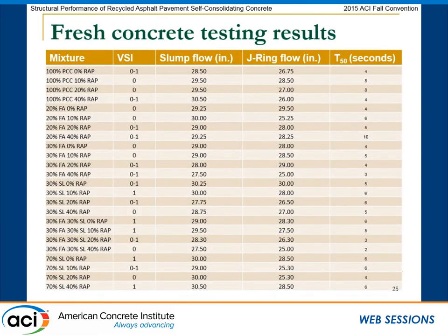If you take a look at the results, all of the mixes had a very reasonable VSI from 0 to 1, and that's acceptable. Here is slump flow. You can see all of them had reasonable slump flow values. The control mix, which is 100% Portland cement and 0% RAP, had a slump flow of 28.5. When 10% RAP was introduced, you can see an even higher slump flow, and 20% and 40% also had a higher slump flow than the control mix.